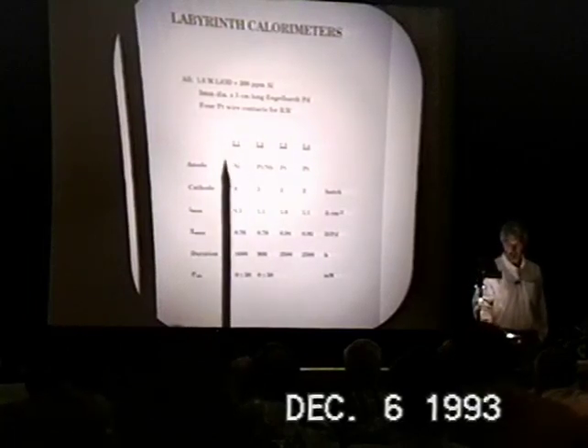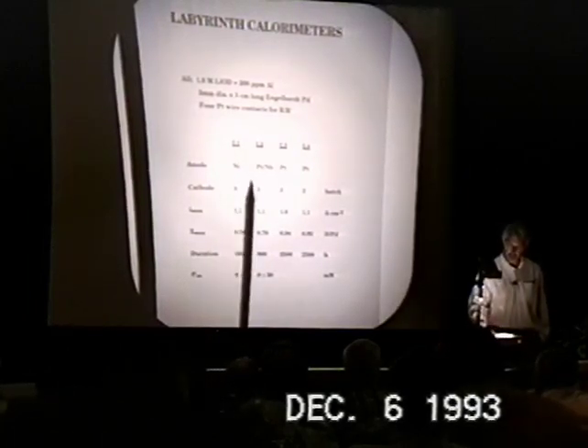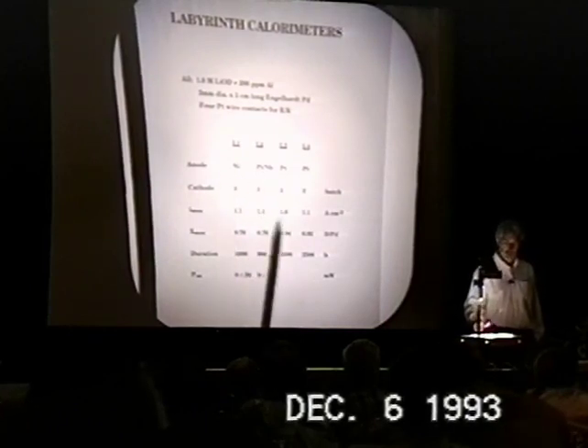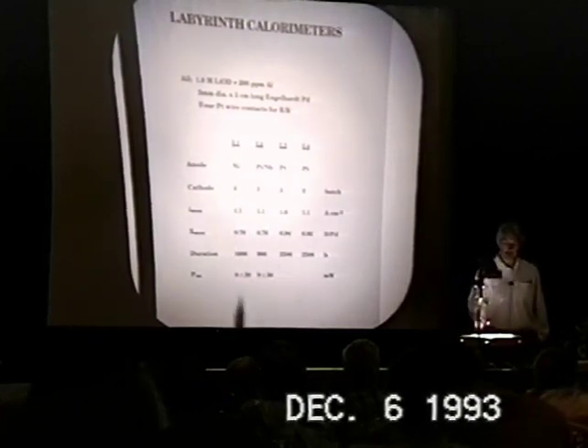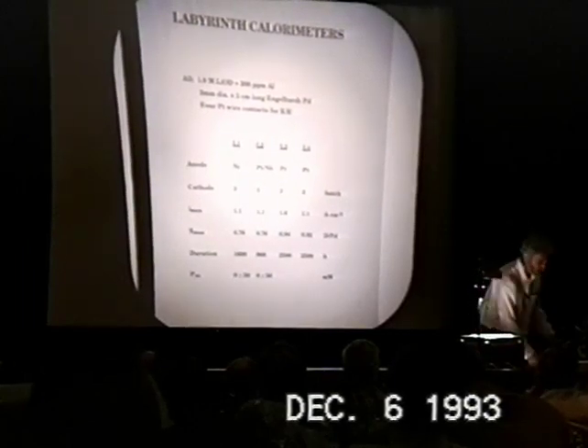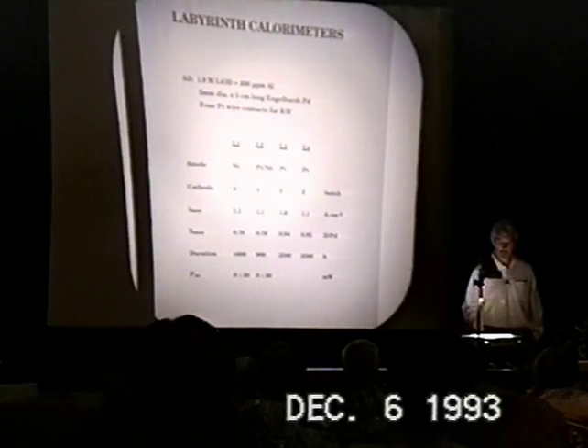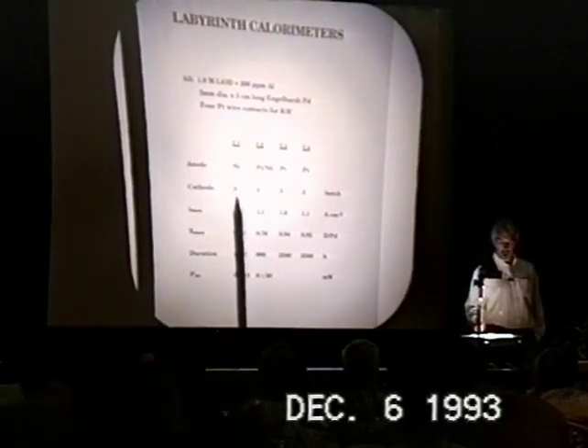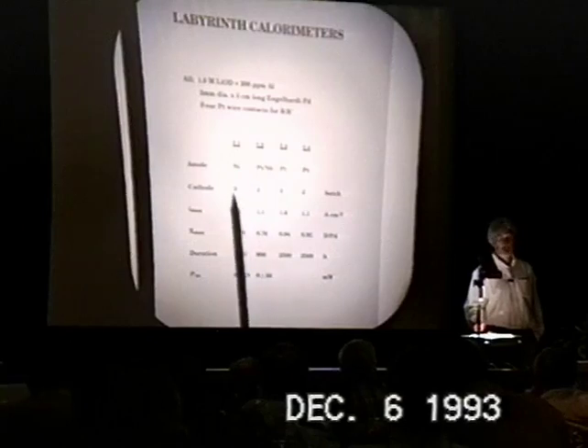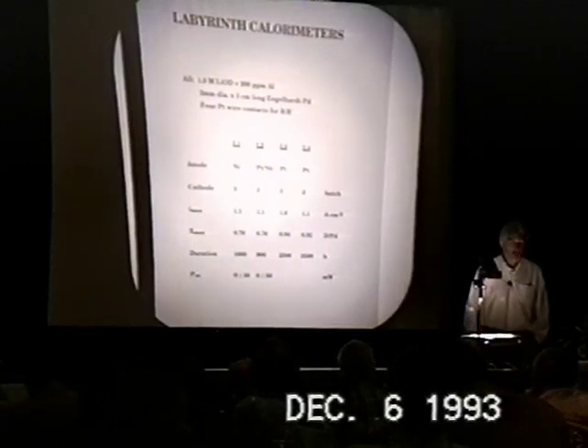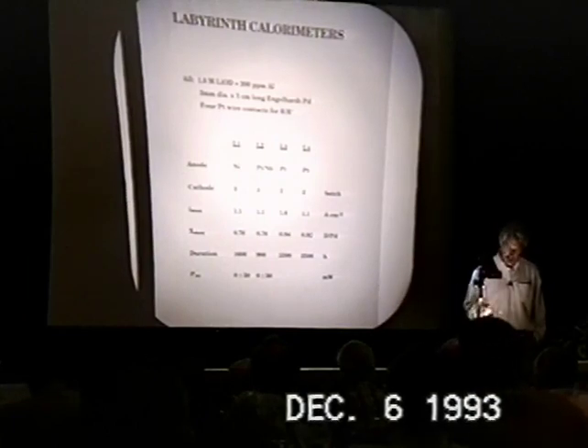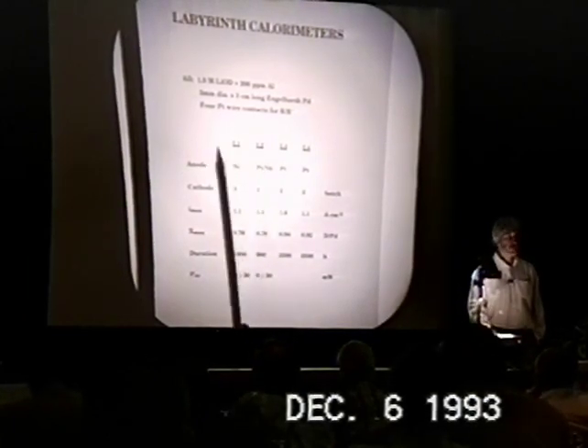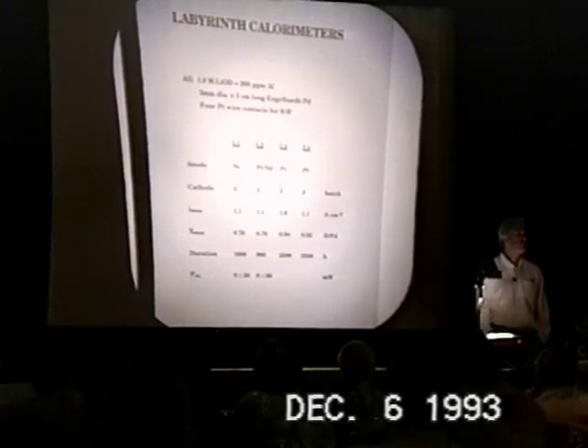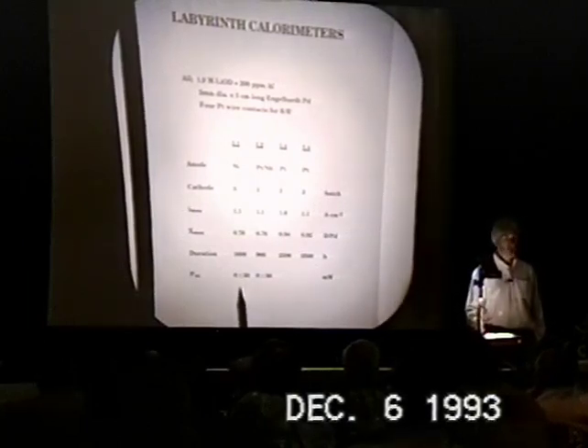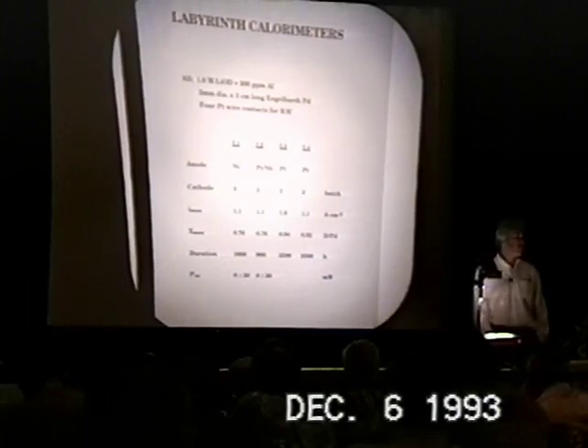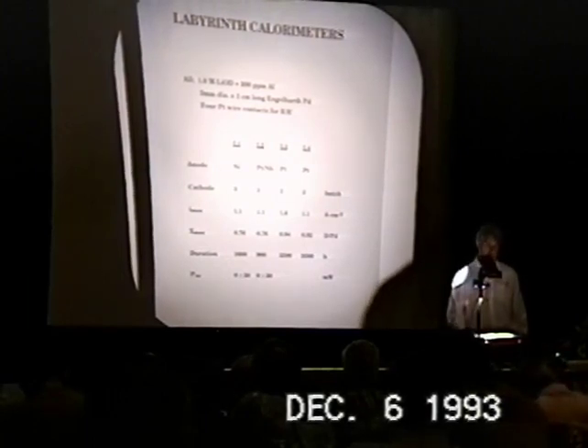It's unfortunate because nickel is cheaper, if nothing else, than platinum, but we abandoned the use of nickel in all of our cells. Second, a platinum niobium anode, which we also found not to be especially satisfactory. Two cathodes, L1 and L2, are batch 3 palladium hard material, which by itself does not give good loading. The results from these two cells were many hundreds or thousands of hours of calorimetry, and the cells maintained themselves within their thermal balance within the sensitivity and accuracy of measurements, which is 50 milliwatts.